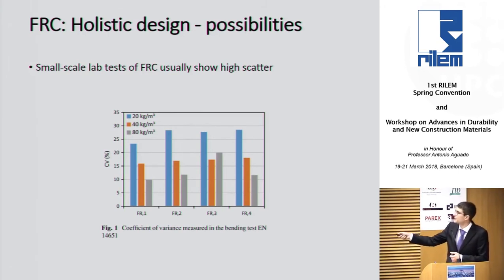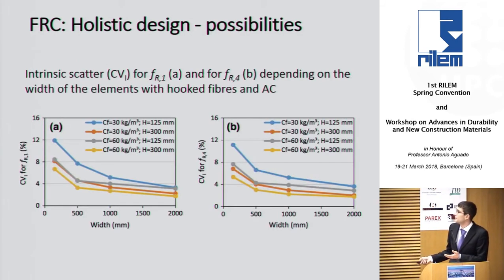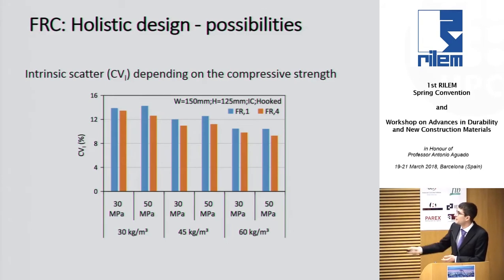You see here a compilation of results from the literature, the coefficient of variation depending on fiber content, for different residual strength values. You see that it varies with fiber content, reducing with fiber content. So we can now, with this type of simulation, predict the variability, understand how it works, see how it reduces with the size of the element. So you see here the coefficient of variation for different sizes of elements also. And even depending on the fiber content, right? So it's a very powerful tool. It's not yet something that can be widely used for design, but it's on the way of getting there.